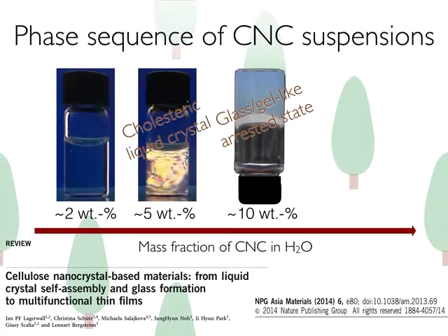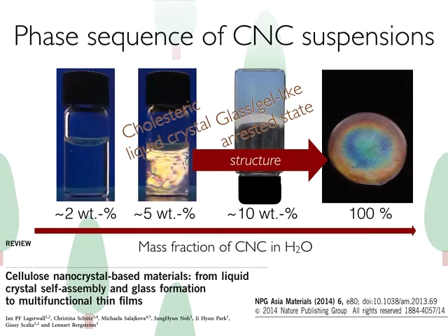And this gel is, in one sense, a nuisance because it prevents us from expanding the liquid crystal phase diagram. It reduces our ability to tune the cholesteric pitch and so on. But on the other hand, in another sense, it's actually a blessing, because if it weren't for the gel state, you wouldn't be able to prepare these films. The gel state preserves the cholesteric helical arrangement that happens at 85 to 90% water, and that's why it's still there when we have evaporated the water completely.